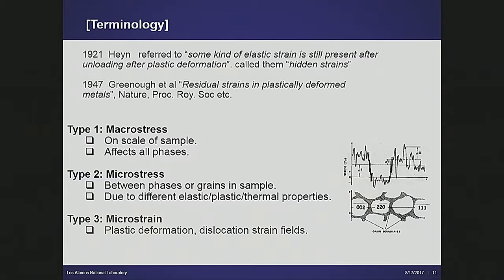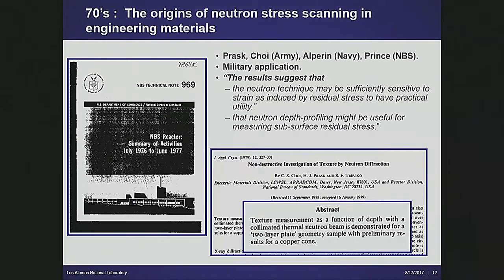The fact that neutrons could potentially touch the problem was first recognized in the 70s, where Hank Prask, who did most of his work at NIST, working with these guys from the Navy, basically made this observation: neutron technique may be sufficiently sensitive to strain as induced by residual stress to have practical utility, right? Neutron depth profiling might be useful for measuring subsurface residual stresses. It's an observation that, because objects are metal, you can still get an appreciable neutron signal through an inch or so of steel, right? You can make measurements, right? And they made this observation: depth profiling might be useful.